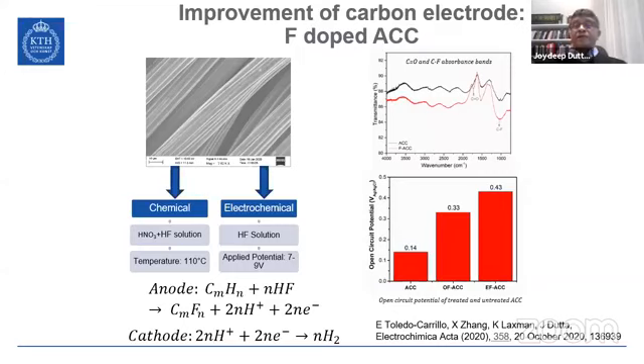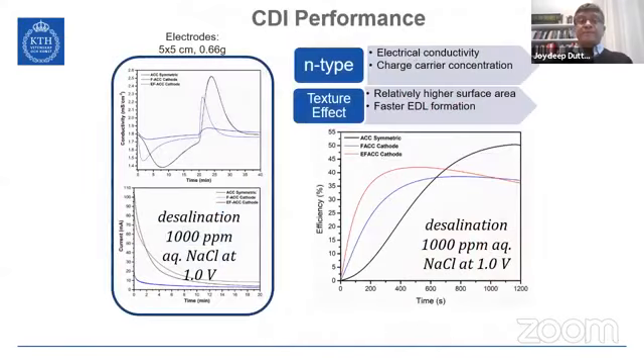Currently, we are solely focusing on modification of the electrode surface. One of these examples is here. By fluorination of the electrodes, we are able to increase the open circuit potential, and that leads to extremely nice desalination efficiency. We also do some work on water splitting for hydrogen production, and fluorination helps to reduce oxidation of the electrodes. So this is just an example. Again, I will request you to take a look at the steepness of this curve. As you can see, we are able to extract the ions much more quickly. So one can do multiple cycles within a given period of time.